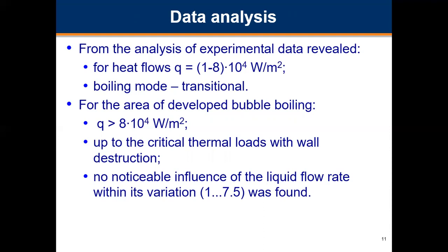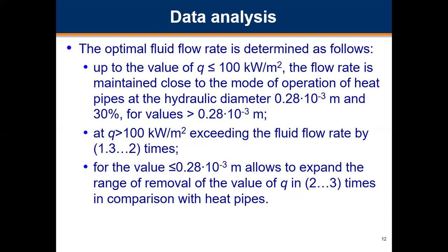For the area of developed bubble boiling, Q greater than 8 times 10 to the power of 4 watts per square meter, up to the critical thermal loads with wall destruction, no noticeable influence of the liquid flow rate within its variation, 1 to 7.5, was found. No influence on the heat transfer capacity of the system for different cell size of the structure, as in heat pipes, is noticed, because neither increased hydraulic resistance of the structure nor a decrease in capillary suction limits the flow of fluid. It is not reasonable to significantly increase the coolant flow rate because there is a redistribution of convection and boiling flows, which makes the system more expensive.